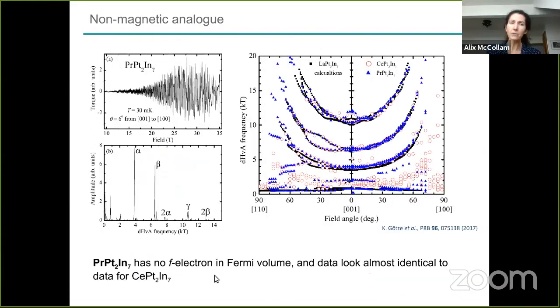We also measured the non-magnetic analog. Single crystals of lanthanum platinum 2 indium 7 are not available, at least not in good quality. I think actually they're not even available at all. But praseodymium, the f-electrons in praseodymium are well known to be localized. So we measured praseodymium platinum 2 indium 7. We had nice single crystals of that. So this is definitely a localized system. The data look very nice.